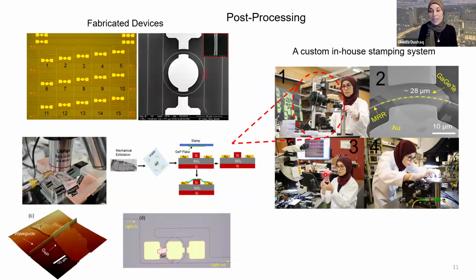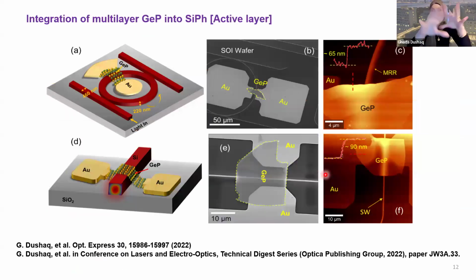This is what I call deterministic transfer, because you really need to transfer these 2D materials onto the photonic chip in a very precise manner. These are uncladded chips, and when you have material scattered everywhere, it will create lots of losses. That's why we need a deterministic transfer, where the material should lie between the electrodes and where the active layer should be. So you define the active layer by defining the region of interest that you really want. I call this a deterministic transfer process. You can see here a very clean transfer onto a silicon waveguide, and this is one of the examples, on germanium phosphide material for optical detection.